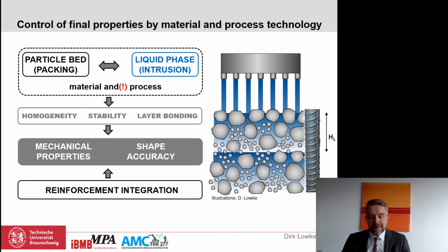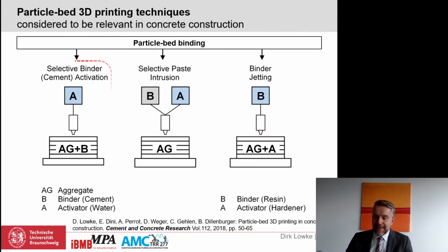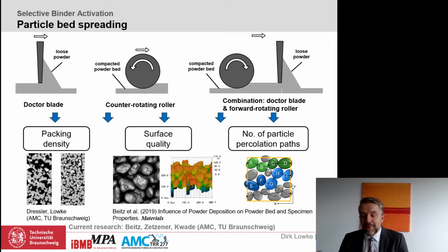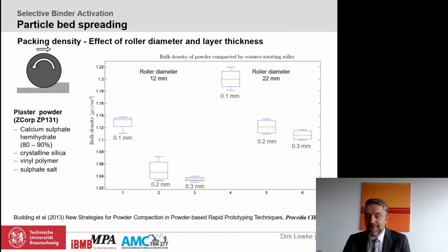Let me firstly address the selective cement activation technique. Here we start with the particle bed spreading process, and from the process technology side, we have a wide range of tools at our disposal. Usually, doctor blades or rotating rollers are applied for the particle bed spreading process. These tools significantly affect the packing density, the surface quality of the particle bed, as well as the number of particle percolation paths. We could see in the state of the art, for instance, that components manufactured by selective cement activation are characterized by a low density and strength.